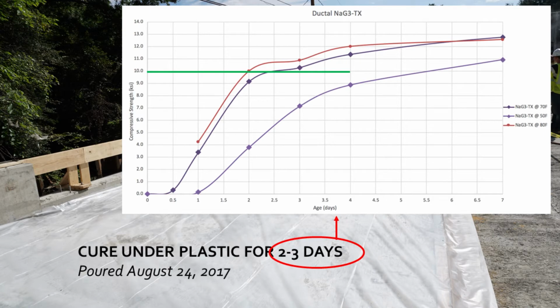And so this is the strength curve of this material. We've generally been targeting about 10 KSI before opening to traffic. And depending on your temperature out there, you're going to get that in about 2 to 3 days with this particular mix design. We're working on improving that to hopefully get that in a day or so, and that's ongoing.